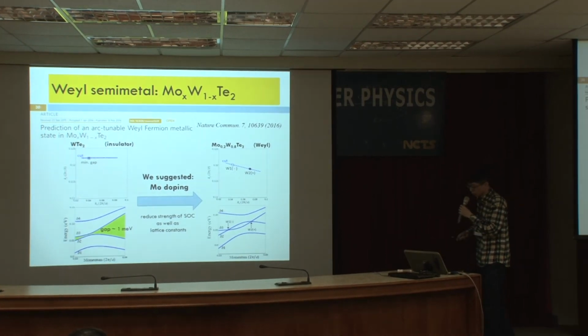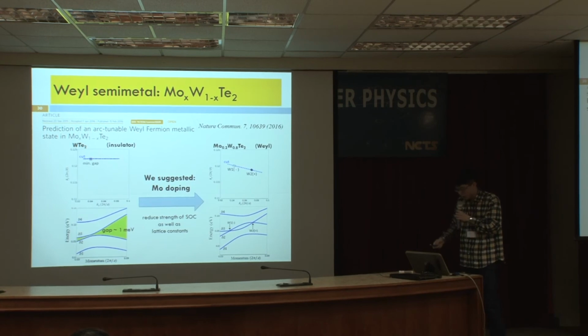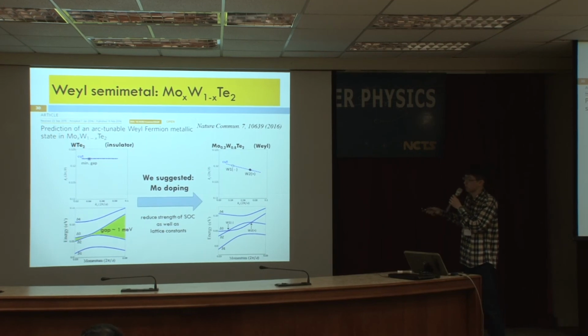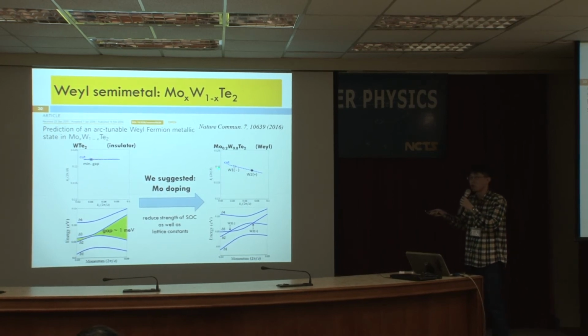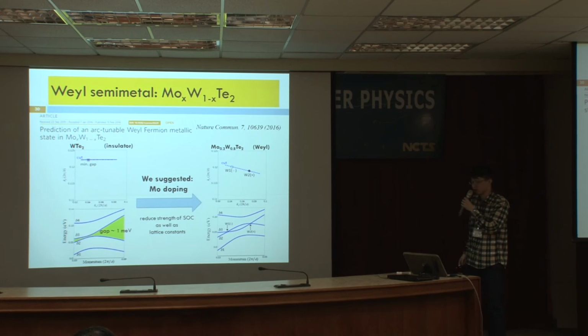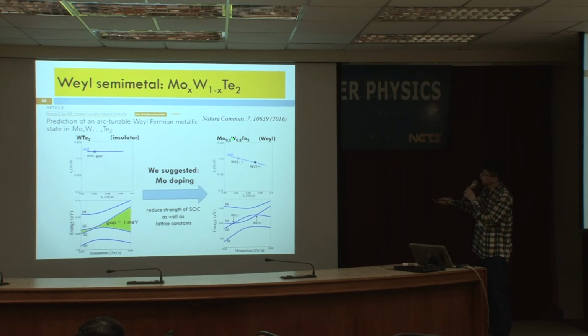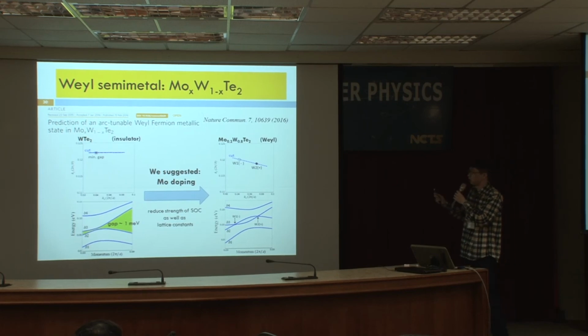We have checked lattice constants from different experimental data, and we found that in some cases molybdenum telluride has 8 Weyl points, while with some experimental lattice constants we only get 4 Weyl points. So it's very sensitive to the lattice parameters. In this system, we choose 8 Weyl points in molybdenum telluride for doing the linear interpolation.